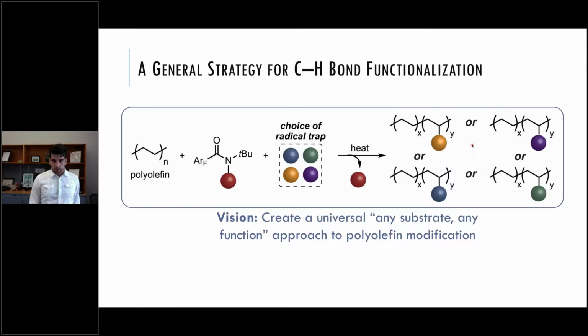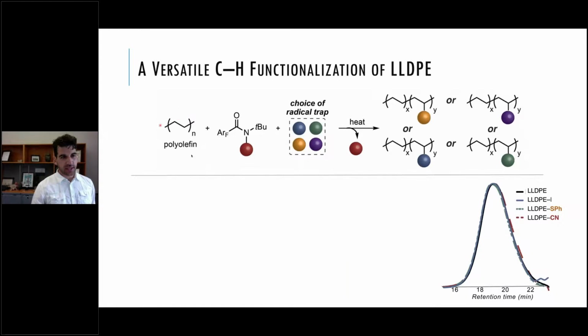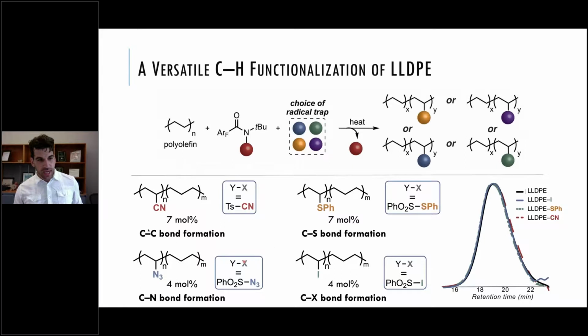So we came up with a new way to do a similar reaction, where actually we could have a choice of anything we wanted to add to a polymer, and we engineered this reagent in a way so actually whatever we added into this reaction would be connected to the polymer. So we call this a universal any substrate, any function approach. So now again, we took linear low density polyethylene, that is a polyolefin here. I'm not showing you the actual structures here because we're still getting IP on these specific chemical reagents. And we could make carbon-carbon bonds to the polymer, carbon-nitrogen bonds to the polymer, carbon-halogen bonds to the polymer, carbon-sulfur bonds to the polymer.